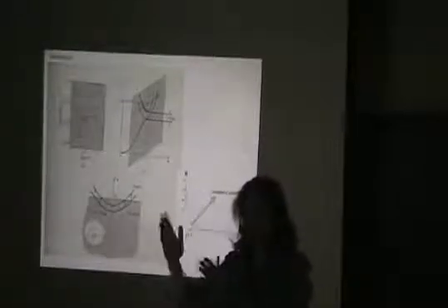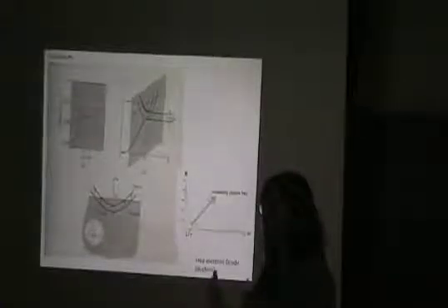Typically there's absorption at some frequency. Let's say there's absorption at a particular frequency, omega naught. In epsilon 2, that is where there was a peak. If you go back and look at reflectivity, you would see a depletion at that frequency. You would say, this light got absorbed. So whatever is the complementary color, if something is yellow, the complementary color of yellow got absorbed, hence we are seeing yellow. Is that clear?